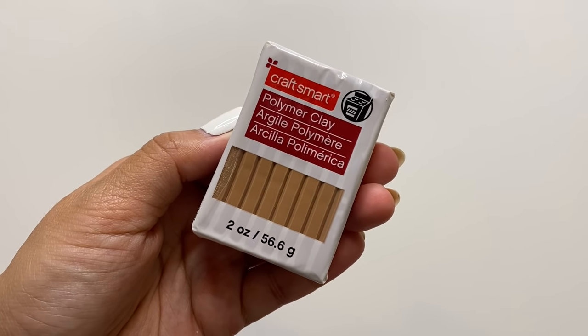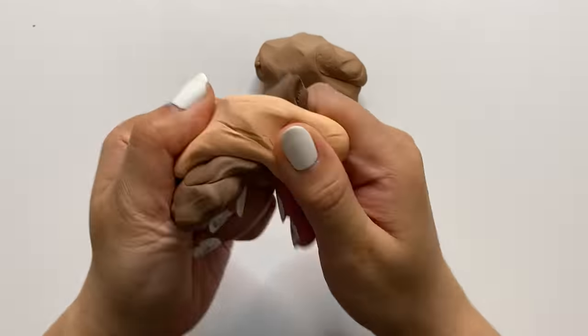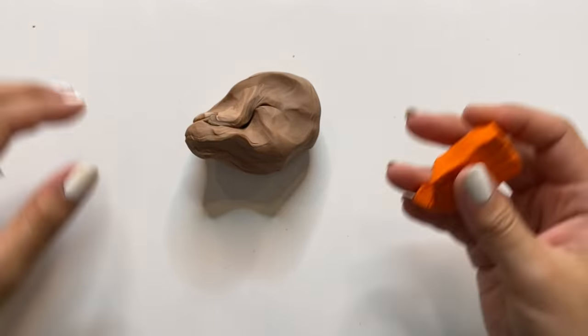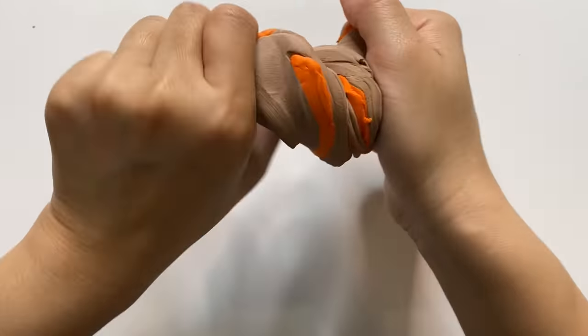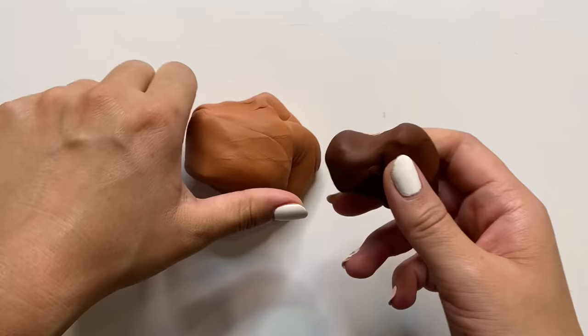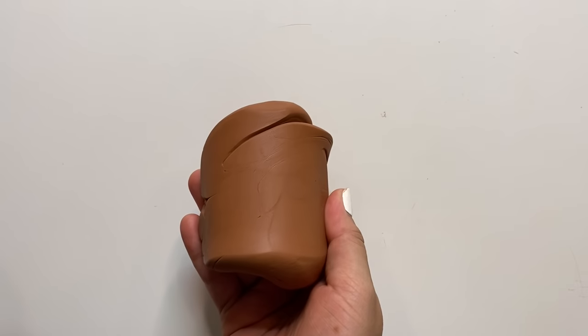For this next mirror I'm going to create the hand mirror from Urban Outfitters using oven-baked polymer clay again. I'm going to mix a bunch of different brown clays together — I find it easiest to knead the clay first so it's nice and soft, then twist them together and wedge the clay onto the table until the color is nice and even. If you're mixing different brands or types of polymer clay, make sure you read the instructions to see what temperature it bakes at. Whatever clay has the lowest baking temperature is what you should go with to avoid burning it. One of the color clays I'm mixing bakes at 230 degrees versus the 275 degrees the rest bake at, so I'm going to bake it at 230 degrees. I used a bunch of different color clays including oranges, pinks, and browns, which created the perfect color to match the original piece.